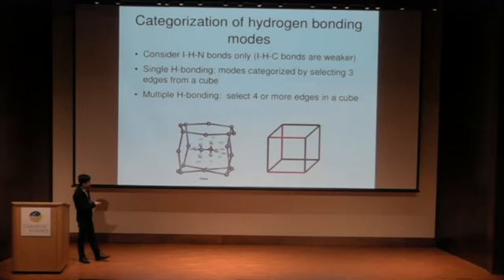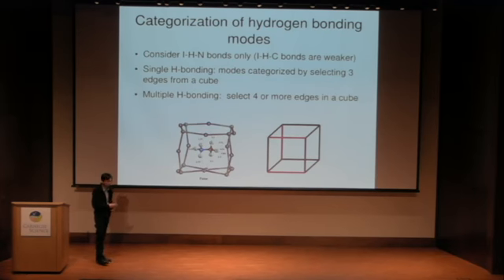So in this figure, if you look carefully at the distance between hydrogen and halide atoms, they're a lot closer for the ones on the nitrogen end than on the carbon end. So one simplification I'm going to make is that we can ignore those hydrogens on carbon and just look at 3 hydrogen atoms per molecule and categorize where those are bonded to.